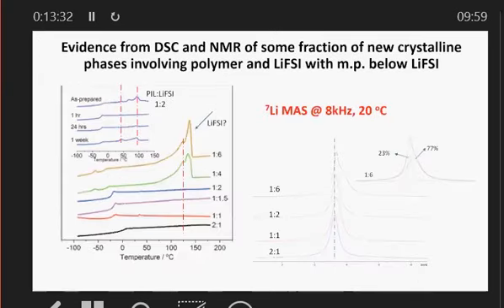So just to try and explain why we got the conductivity decrease, we had a much more careful look at the DSC traces. And here, what we have on the left-hand side is the DSC traces for the various compositions, and we see that the black, red, and purple trace up to 1 to 1.5 is just a Tg. We see the 1 to 2, we see a Tg there, but in the as-made material, we do actually see a couple of other transitions, which are indicative of other phases forming in the material, and we see that much more clearly as we go to higher salt concentration.